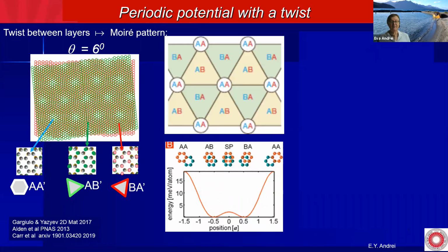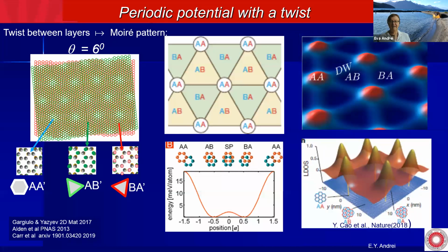So it turns out that making an AA region is very energetically costly. It costs about 20 milli-electron-volts per atom, whereas the AB regions and the domain walls are much cheaper. So immediately you notice that this will give you a periodic potential. When you look at the height profile, the AA region, because of its costly energy, is a little bit higher than the other regions. So you can see this in STM, for example, and the density of states is higher again on the AA regions. So this is a recipe for creating a periodic potential.